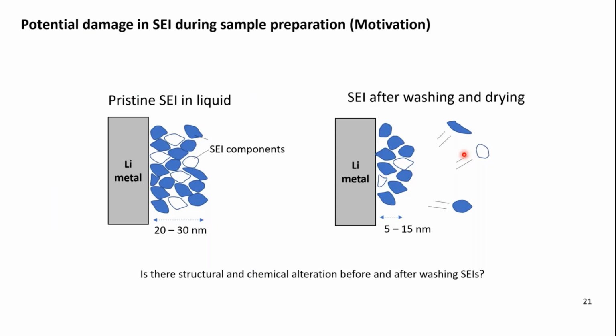In most works, SEI has always been washed by an inert solvent. So we need to wash off excess electrolyte, otherwise it is difficult to achieve electron transparency. However, in real batteries, SEIs are always immersed in liquid electrolyte. So there has been a question of whether the SEI is the same before and after washing away the liquid electrolyte. So what I was wondering is whether there is a structural and chemical alteration when you wash the lithium deposits in liquid electrolyte. Therefore, I decided to preserve the liquid electrolyte in this case.